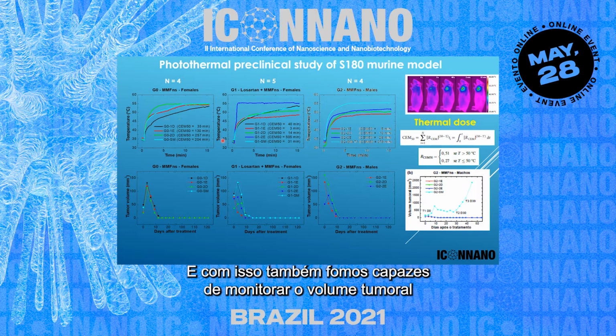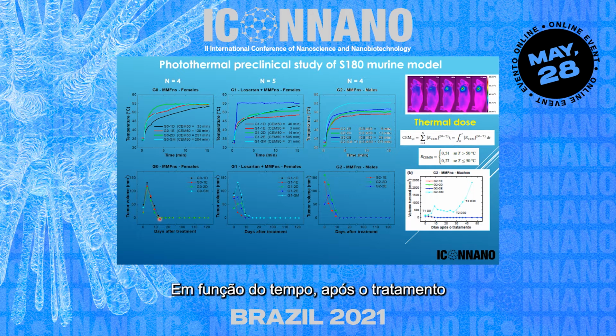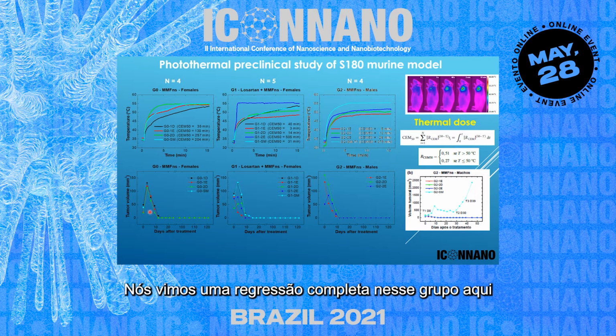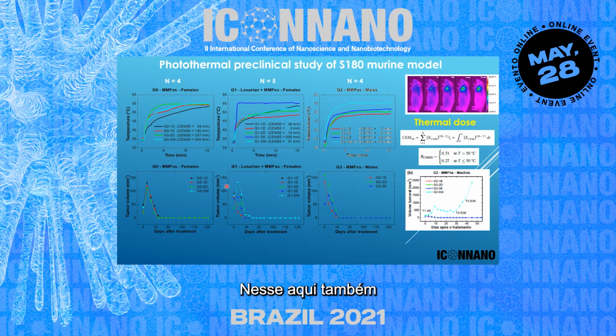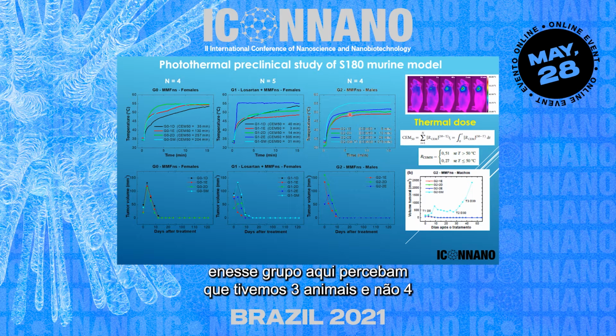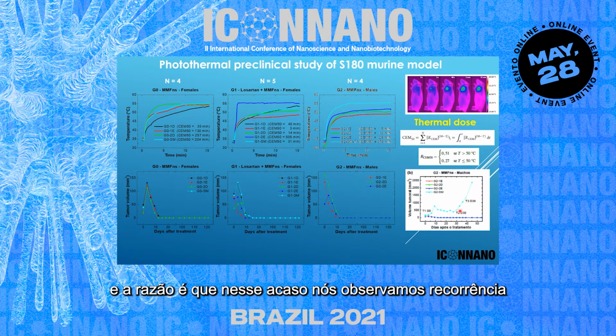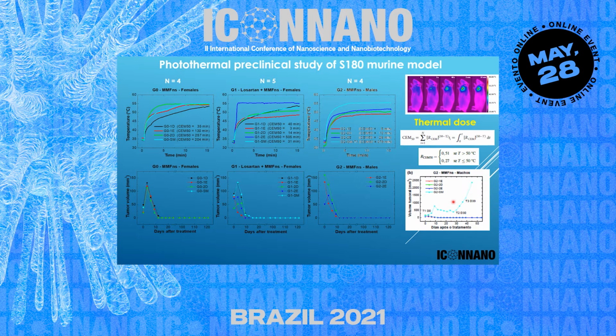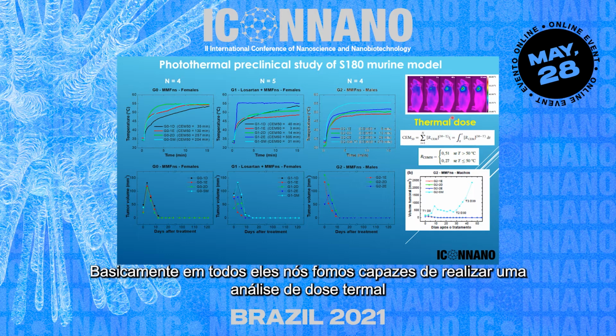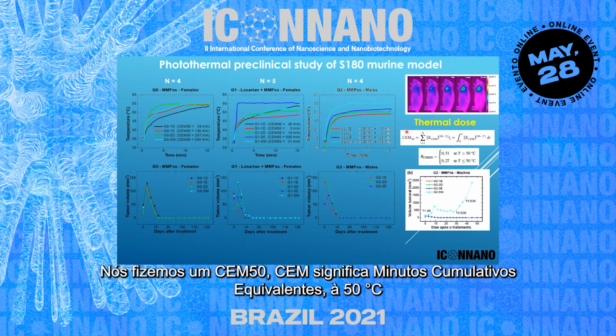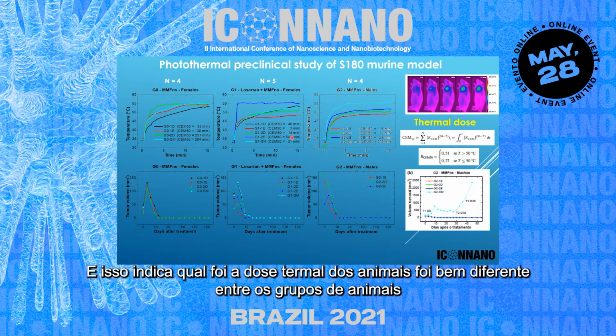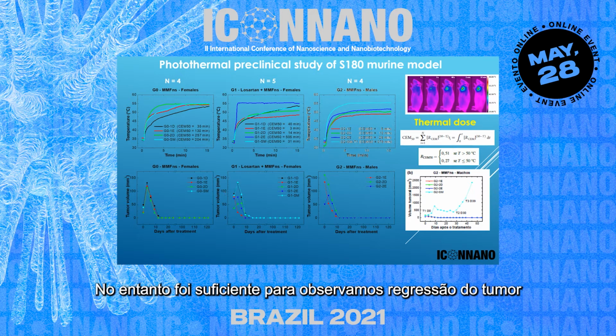And with that, we were also able to monitor what would happen with the tumor volume as a function of time after the procedure, after the treatment. We do see a complete regression for this group here, this one here also, and this one here. Notice that we have 3 animals here, not 4. The reason is that we actually observe for one of the animals recurrence that we will discuss very soon. And basically, all of them, we are able to do a thermodose analysis. We decided to perform a CEM 50. CEM means cumulative equivalent minutes at 50 degrees Celsius. And this can indicate how is the thermodose within the animals. The thermodose within them was quite different between all those animals groups. However, it was enough for us to see complete tumor regression.